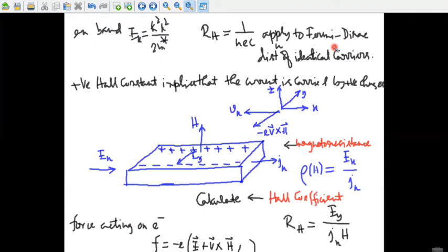The expression becomes somewhat more complicated if both electrons and holes contribute to the conductivity, as is considered in p-type or n-type semiconductors, where both majority and minority carriers are involved in charge transport. For the monovalent metals, the calculated concentration of valence electrons perfectly matches the experimental values and gives quite satisfactory results. However, the sign of the effect in beryllium, zinc and cadmium is opposite to that predicted for electrons.